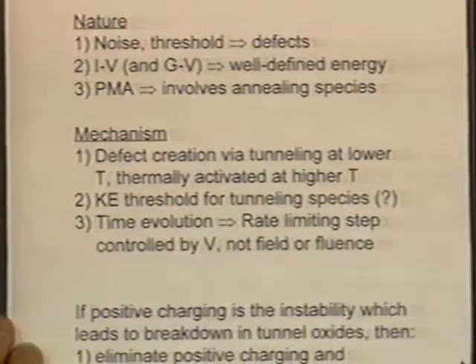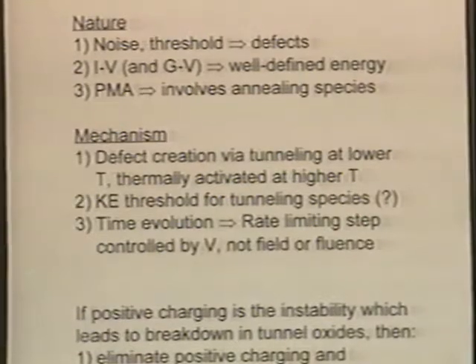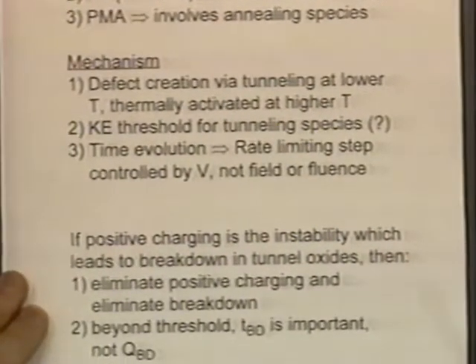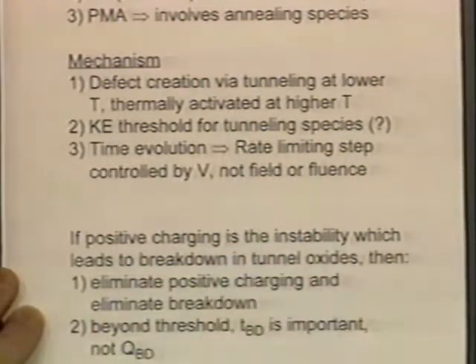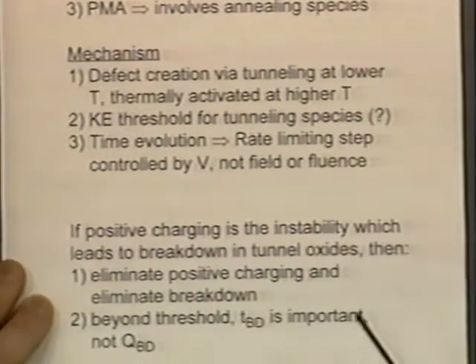Post-metallization annealing suggests that an annealing species may be involved. Maybe what we're doing is breaking a silicon-hydrogen bond. The mechanism for this occurs by some sort of tunneling process. That's what I showed you in the configuration coordinate diagram. At lower temperatures, it's tunneling; at higher temperatures, it's thermally activated.